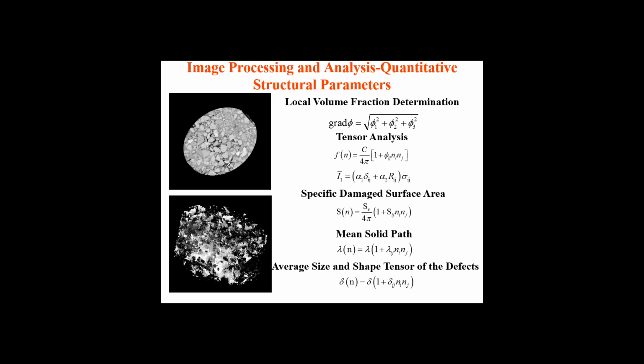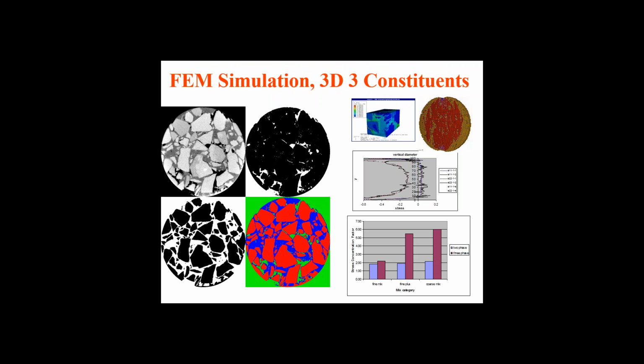We developed various methodologies to quantify these parameters, and use these parameters as potential genes of material behavior. Okay. And then with this one, we incorporate 3D three-phase material simulation using the discrete element approach and the indirect tensile test. Right? Using this methodology, we actually successfully ranked the mixes' performance of the WesTrack project. The WesTrack project has three mixes: the fine mix, fine plus mix, and the coarse mix. And the test results showed that the performance was contradictory to the understanding. But using this image analysis, when you take into account the material structure, we successfully ranked the performance of these three mixes.